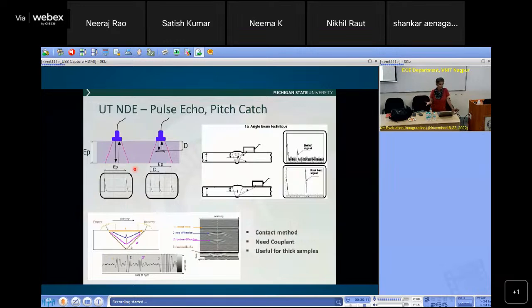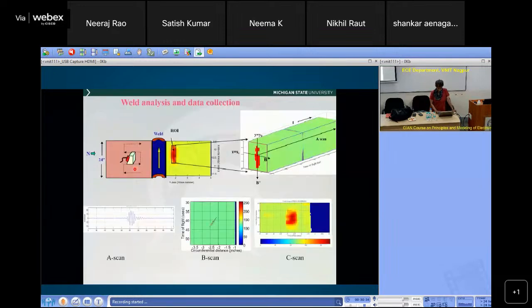But again, it's not always convenient to immerse a big sample. It's probably very convenient for submarines, which are already immersed. But for many samples, it's difficult. That's why the other one is called contact. It has to be in contact with the sample. You have to put the couplant and you have to touch the sample. There's maybe a film of the couplant, very thin. So those are some disadvantages.